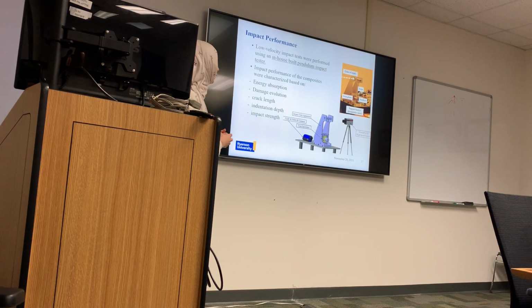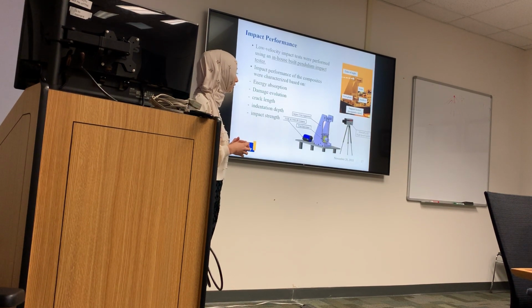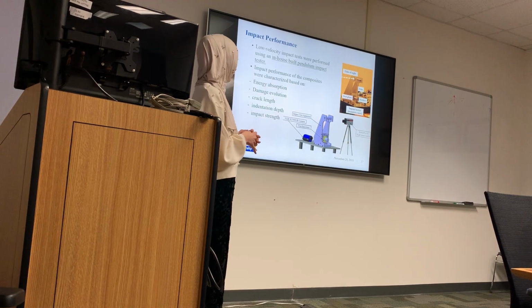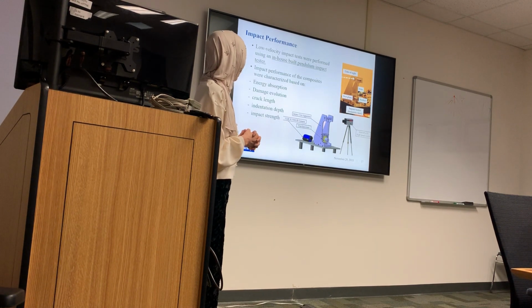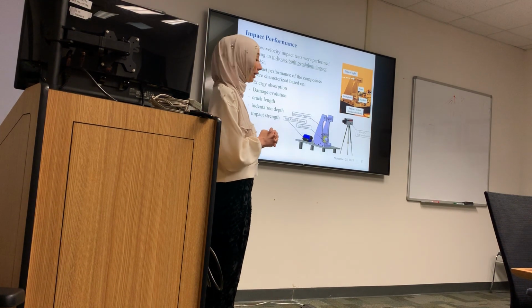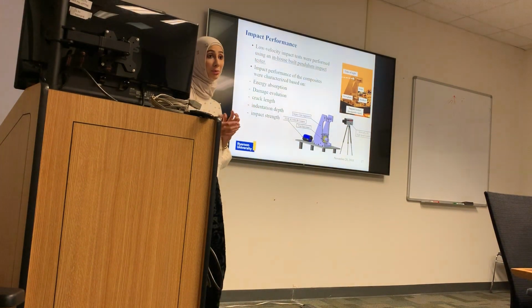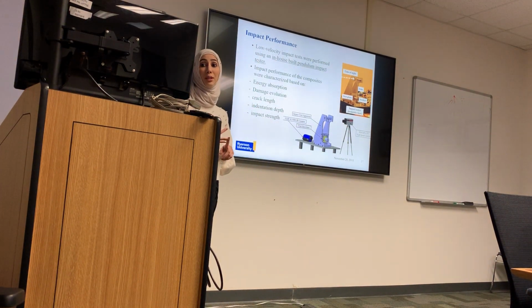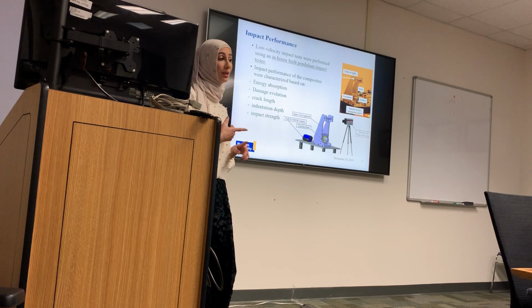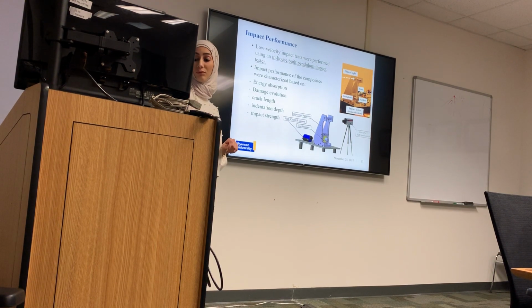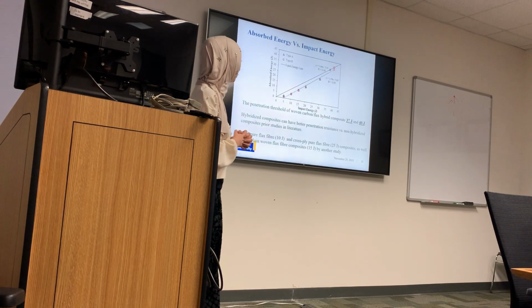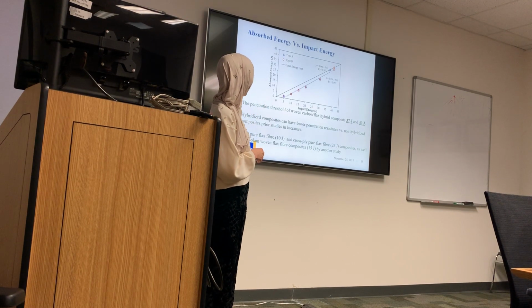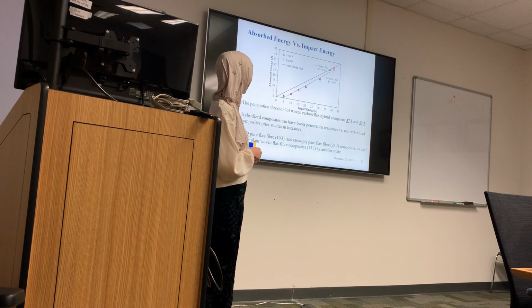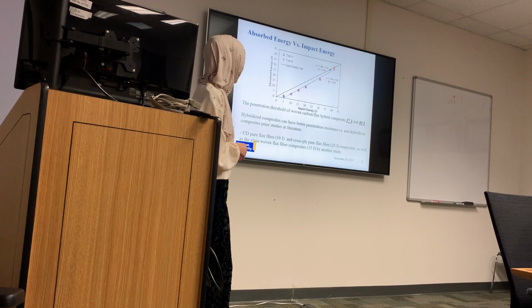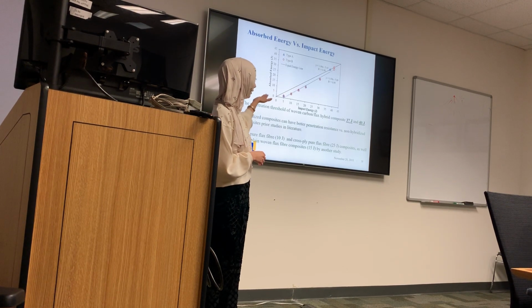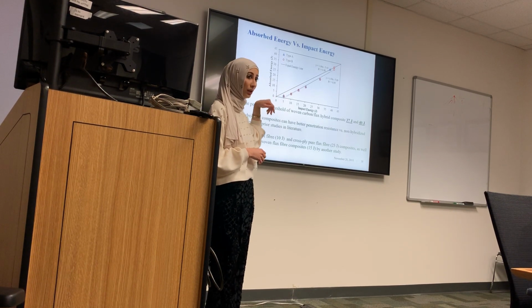I also performed a drop impact characterization on the hybrid composite using an in-house pendulum impact tester. I characterized it based on energy absorption, damage evolution, crack length, indentation depth, and impact strength. We see here the relation between the impact energy applied and the absorbed energy for both composite types A and B. Both of them show a linear relation up to 30 joules.